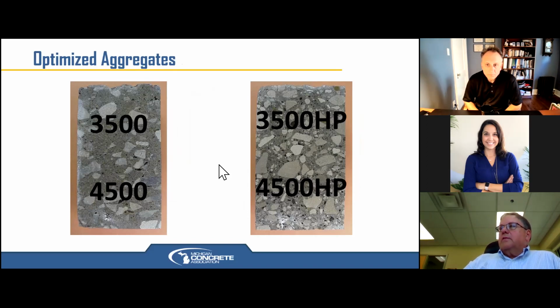Our strength, when we took a standard P mix from MDOT, we went from a specified 3,500 mix that actually reached usually around 4,500 PSI. Once we went to well-graded, I think our breaks are now around 5,500 PSI. So we gained quite a bit of strength by just relying on the aggregates. And at the same time, we took another half a sack of cement out of our mix designs.